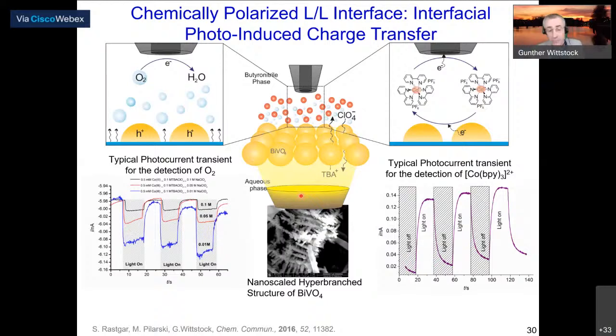So now when we want to exploit that, we need to arrange semiconducting oxide particles at an interface between such layers. Most of the experiments are made with hyperbranched bismuth vanadate particles. They look like this. Then we can exploit photoelectrochemistry at these layers. We detect the products with a microelectrode over such layers, or we use mediators and then manipulate the system by switching light on and off.